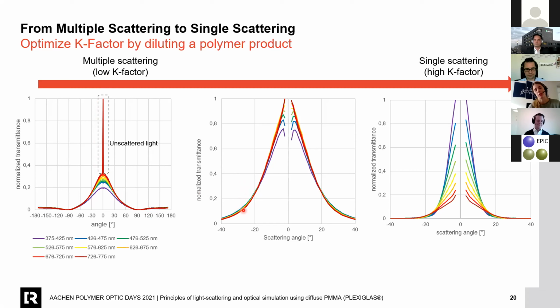Here is the question: do we have multiple scattering or is it single scattering? As Anna said before, Mie scattering is dependent on wavelength, so the wavelengths should be separated. In this diagram, they are mixed, especially in the flanks. So we can say that we have multiple scattering as well, and we have to decrease the concentration again to have a higher K factor and to separate the wavelengths. In this last measurement, all wavelengths are separated and you see them, and we can say that this is a single scattering event. If you decreased the concentration again and again, the diagram wouldn't change.